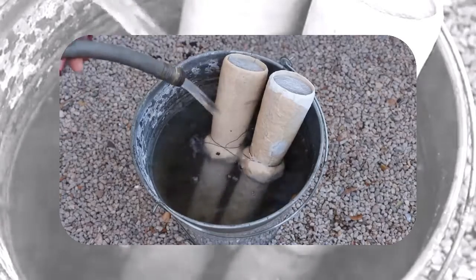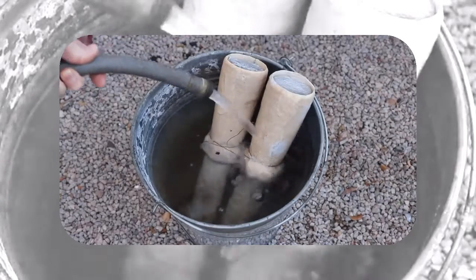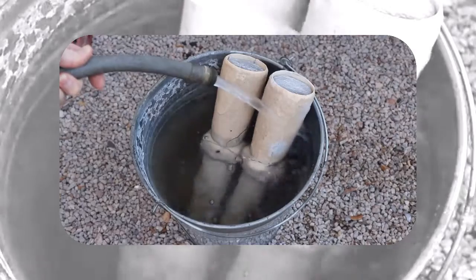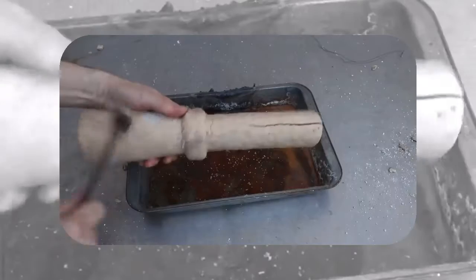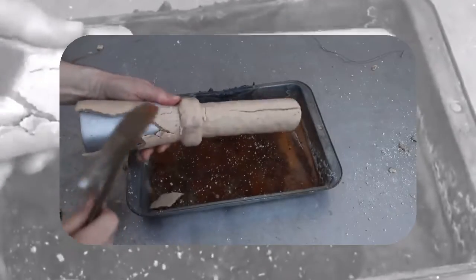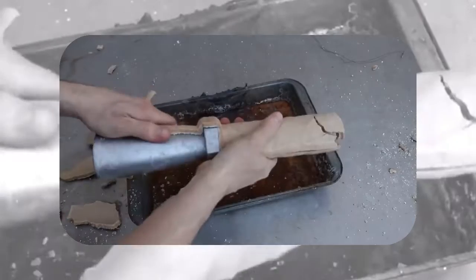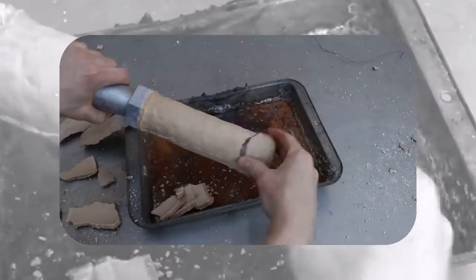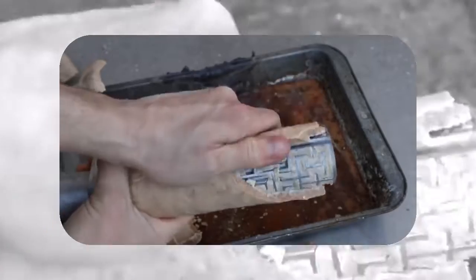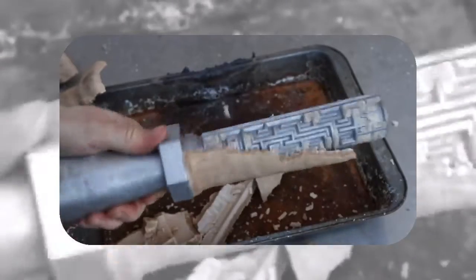When I was done, I submerged the castings in water to help cool them down. Unfortunately, this didn't soften the shells at all, but it did help keep the dust from floating around as I broke apart the molds. Breaking off the shells is definitely the most exciting part of this process because I finally get to see what the castings look like.